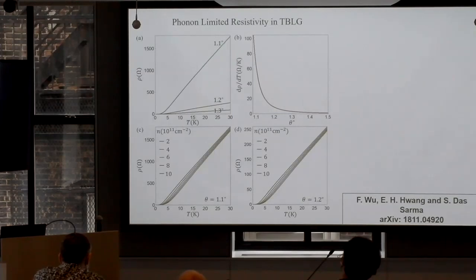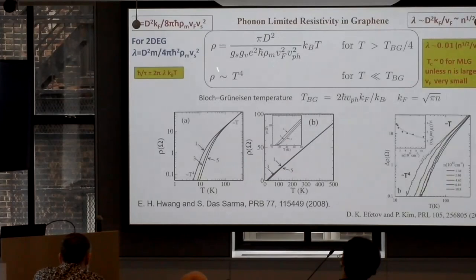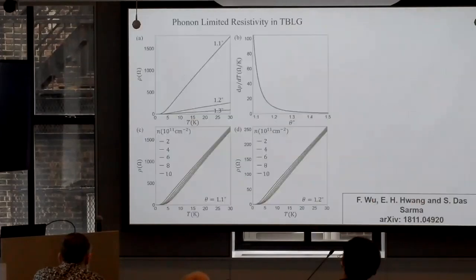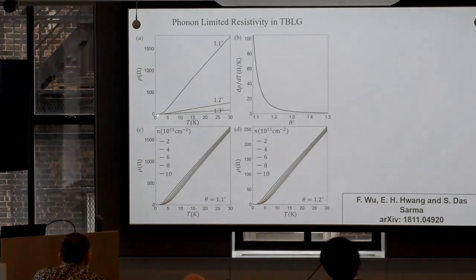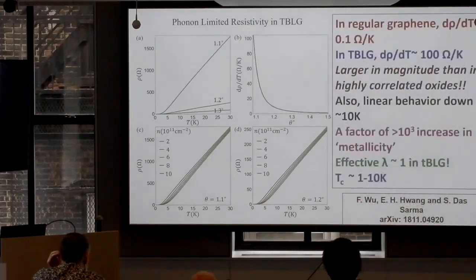All that is coming in is this. This is basically this formula recycled, doing the full calculation in between, recycled now with Bistritzer-MacDonald band structure for graphene velocity. So as you can see on this plot, the monolayer graphene will be basically along the horizontal axis. And as the angle goes down, resistivity should go up enormously. And d rho dT should show this huge change, 0.1 to all the way 100 ohm per Kelvin, as you go from small twist angle, let's say 1.1 degree, at magic angle in our theory diverges, to regular graphene. And this agreed remarkably with the experiment.